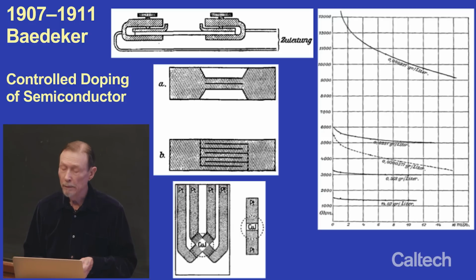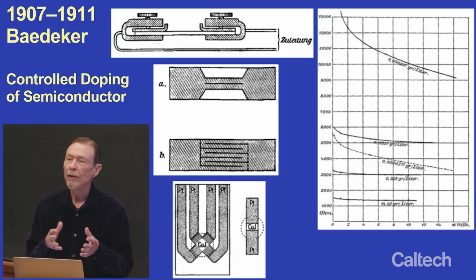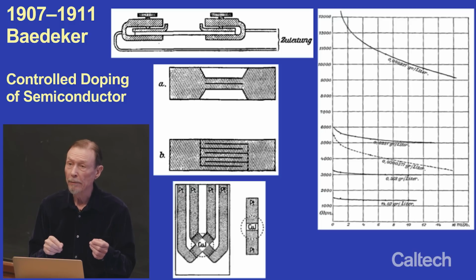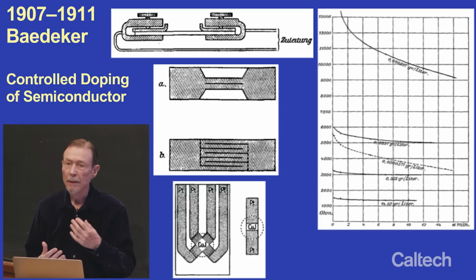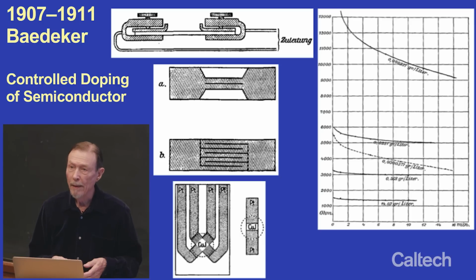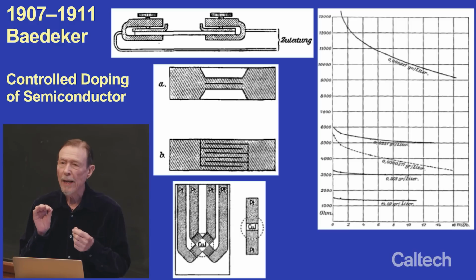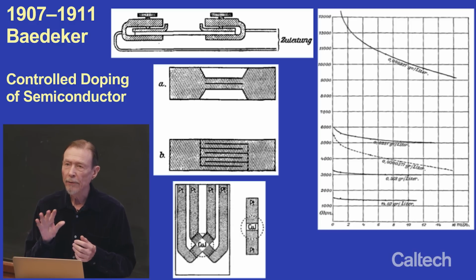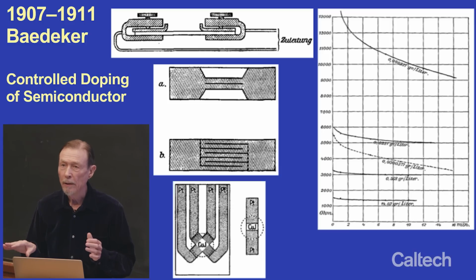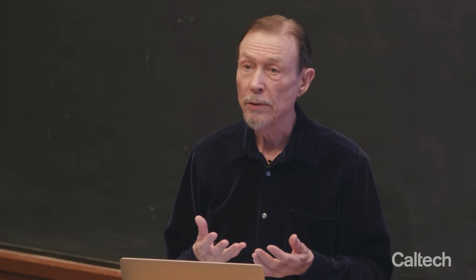But the more iodine you put in, by making the concentration in the fluid that you were treating the copper in have more iodine in it, or you waited longer for the iodine to go into the film, then you got lower and lower resistance. The film was able to carry current better. So it's the first time that people had a controlled way of making a semiconductor of a given conductivity. It was huge. It's a conceptual leap where you now could control the density of things that carried current by controlled chemical treatment. And that's been with us ever since. That process underlies every semiconductor device.